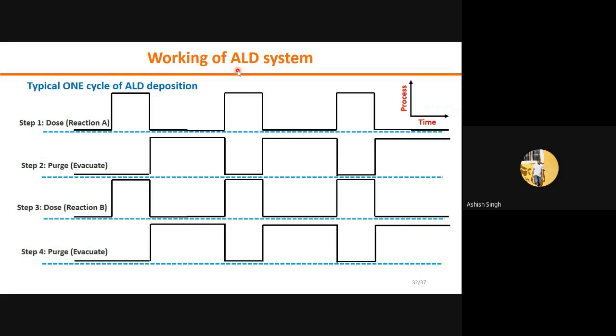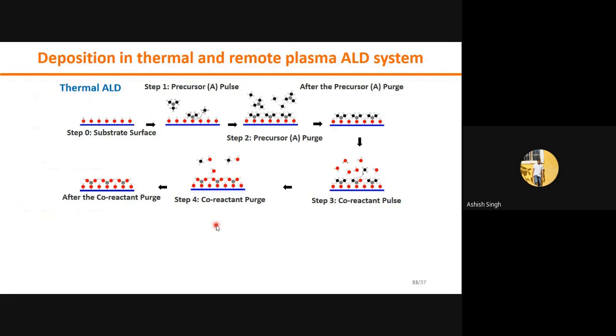This is a typical one cycle of ALD deposition, and it is divided into 4 steps. One cycle means 4 steps we need to run. In the first step, reaction 1 is done as the dose goes in. In the second step we evacuate the leftover unreacted material from the chamber. Then we put the second reactant in the chamber, and the fourth step is to evacuate the chamber. So we can understand it easily here.